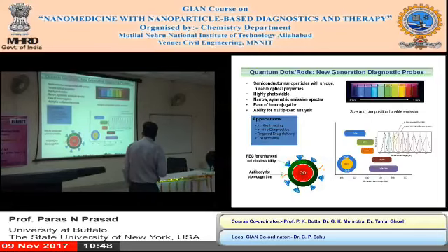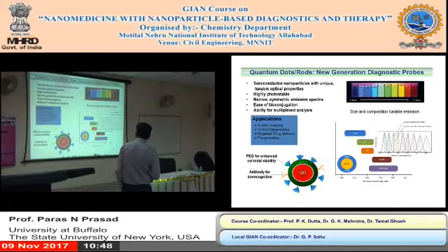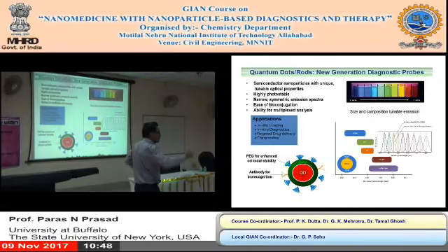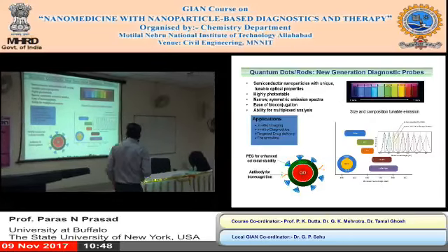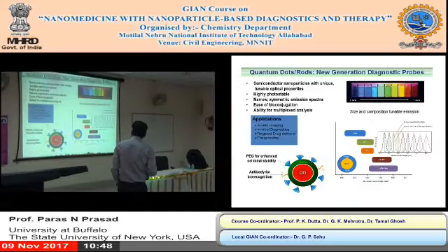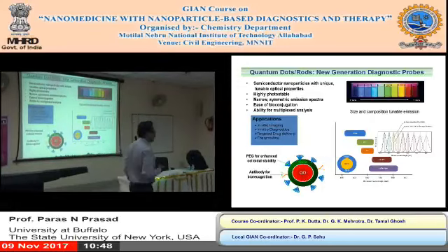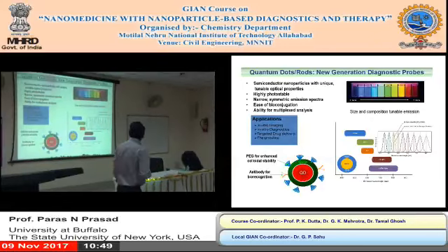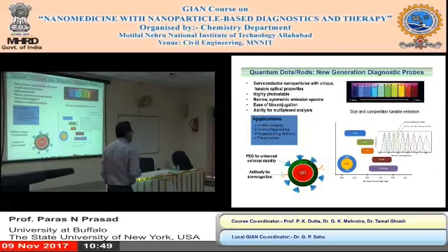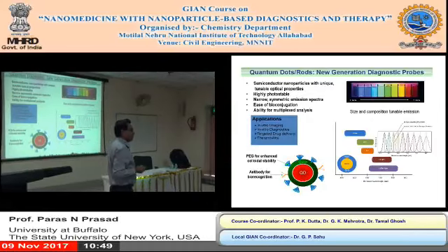Then on the surface, we put these antibodies, remember, with a lock that grabs onto antigen on the surface to attach and get in there. And in addition to that, you put this pegylation group, which is polyethylene glycol, very often abbreviated as PEG. You attach that because it enhances the circulation of the nanoparticle in blood so that it has more time to find where it's supposed to be by this targeting group. So this is the kind of nano formulation you use for imaging if you want to do that.